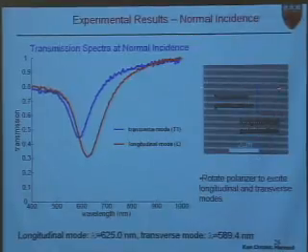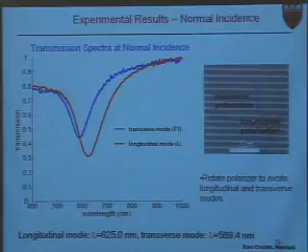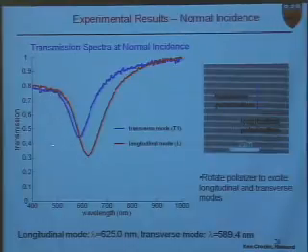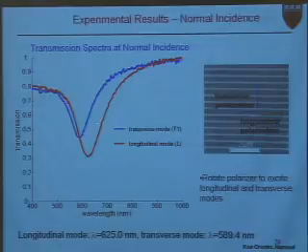The blue curve is when we have the polarization perpendicular to the chain. The red curve is when it's along the direction of the chain. And you notice there's a dip in transmission. So what's happening there? What's happening is that at this wavelength or frequency, we're coupling to the plasmon resonance. So we couple to the plasmon resonance at that frequency to get those electrons oscillating in those enhanced fields, and that leads to a drop in the transmission.